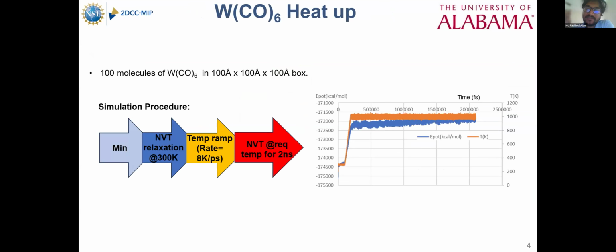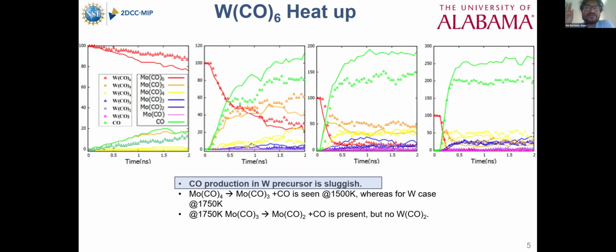And from this energy versus time and temperature versus time graph, we can see that our parameters that we have chosen are actually not bad. They're very much good. And these are some results from that tungsten hexacarbonyl simulations. And we have compared them with the molybdenum ones. And we can see that the straight lines, those are the molybdenum ones, and the triangular ones are for the tungsten ones.